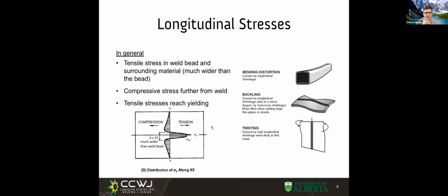So in longitudinal stresses, we have this tensile force around the bead, right? Not just the bead, but the bead and around the bead. If we are making a hollow steel section such as this one, the force that is related to the weld is off-center, and that causes bending. And the Lincoln Procedure Handbook has a formula for that, and you will know where that comes from. But in addition, other things can happen.